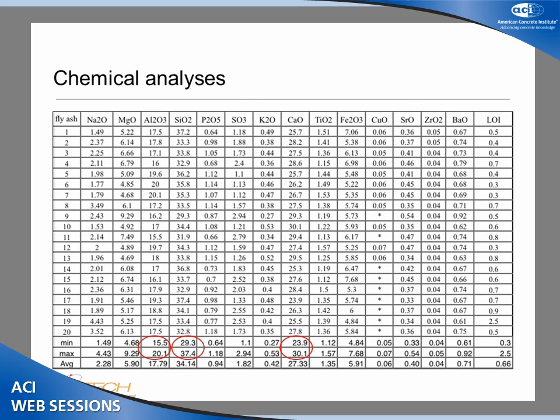That's a terrible slide, so I apologize, a bunch of numbers there. But what I want to show you here is just a range of chemical compositions. As you can see, alumina varied from 15% to 20%. Silica from 29 to 37%. That was probably the highest range. And the calcium ranged from 24 to 30%.